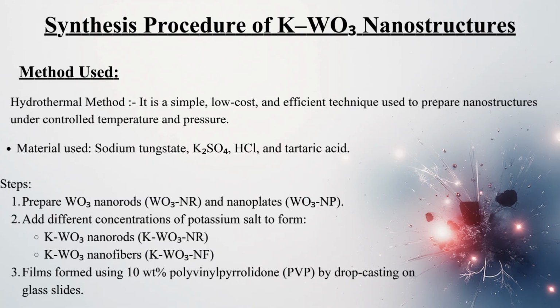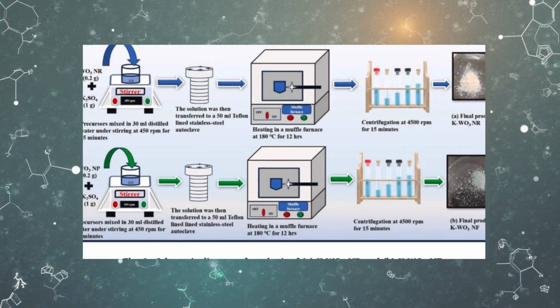The hydrothermal method, a simple and low-cost technique, was used to synthesize the KWO3 nanostructures. The process involves starting with tungsten precursors, adding potassium salt to control the shape, and finally creating a thin functional coating on glass using a PVP binder and drop casting.